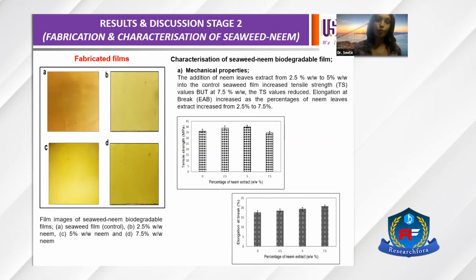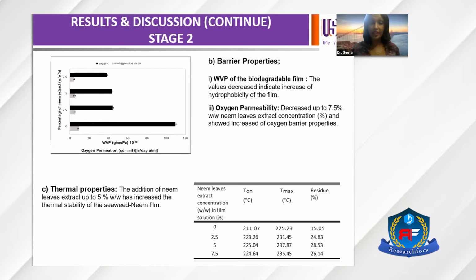This might be due to the interaction between neem leaves and the seaweed hydroxyl groups, that is hydrogen bonding, which strengthens the film structure and enhances the tensile strength. Whereas at 7.5%, which is a very high neem leaves concentration, there is agglomeration. Later I will show you in the SEM, scanning electron microscope, there is agglomeration and holes, so that's why the tensile strength is reduced.